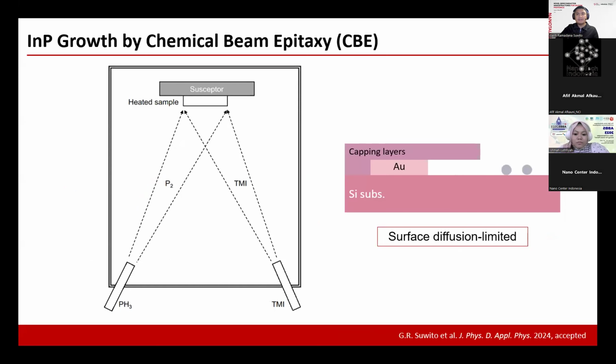In CBE, the pressures are orders of magnitude smaller than in a CVD reactor. Hence, the precursor gases for the case of indium phosphide, TMI, trimethylindium, and precracked phosphine, P2 here, move to the heated sample as a beam, hence the name chemical beam epitaxy. The challenge is therefore to make the precursor adatoms diffuse into the silicon, which is hidden underneath the capping layer. Hence, this growth is said to be in the surface diffusion limited regime.